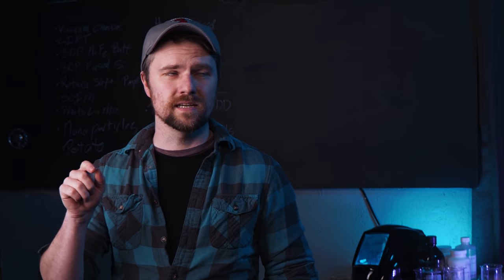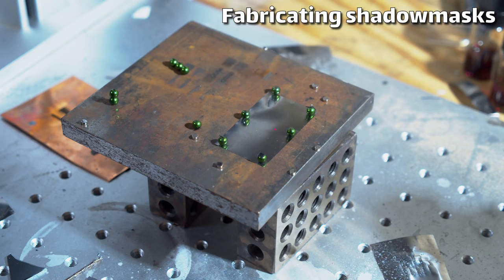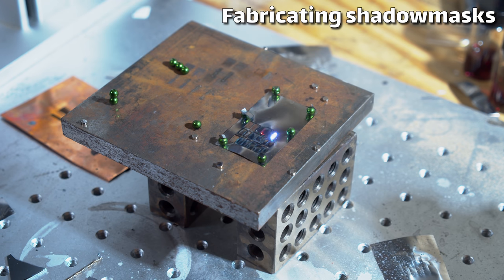I've been doing a bunch of reading and talking to folks and have settled on using titanium and aluminum for the n-type side and using just plain aluminum for the p-type side, and then annealing both of those at 480-some degrees Celsius. In theory that should form an ohmic contact to the semiconductor down below. Aluminum is supposed to form good ohmic contacts with p-type just by itself.